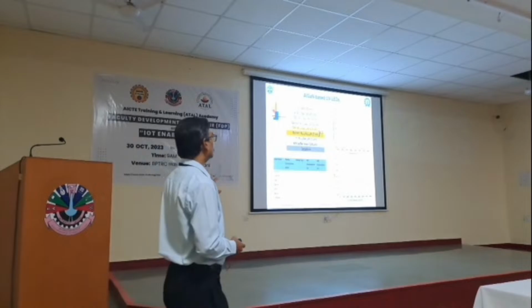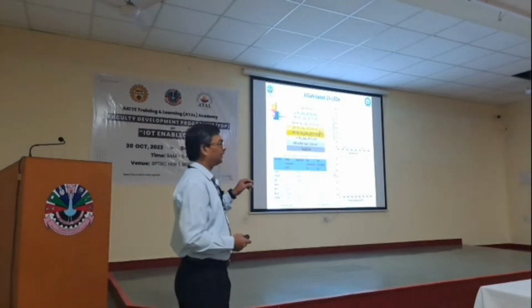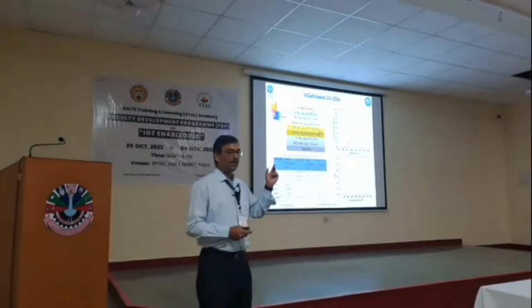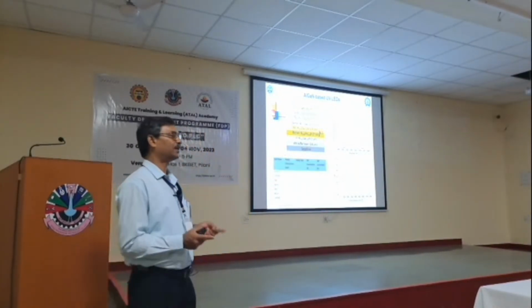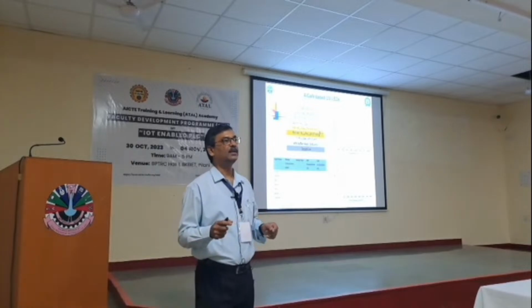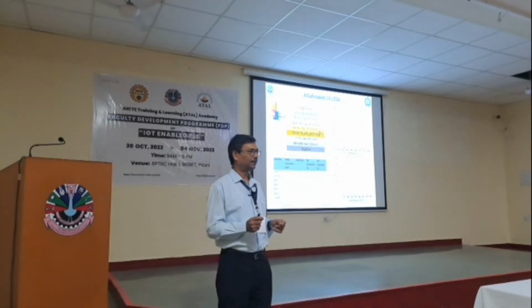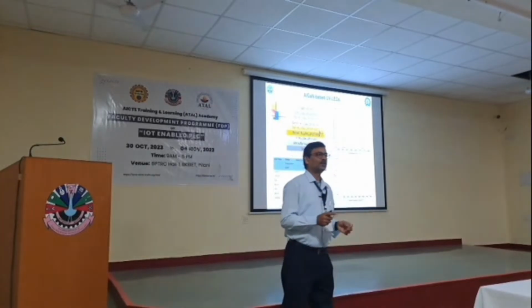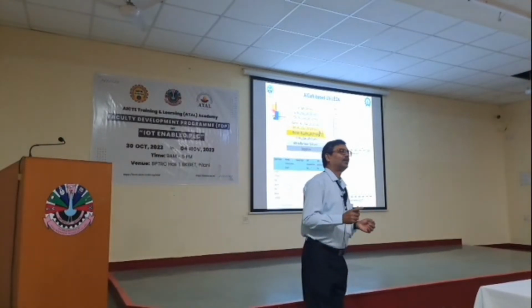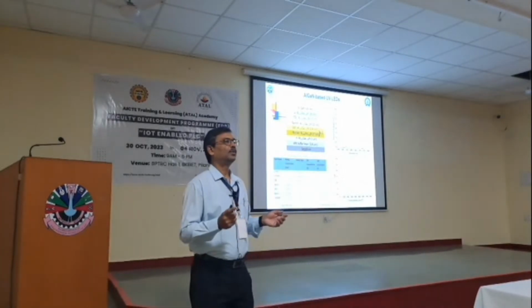Similarly, UV LEDs as well. For UV LED also, gallium nitride is the base material, and with aluminum composition we can go for emission towards UV light. So for blue and white, I just forgot to mention, whatever white LEDs we are seeing everywhere, indoor and outdoor application, blue is its basis. So for that we have to first fabricate the blue LED in the range of 450-460 nanometers emission wavelength, and after that we need to go for the yellow phosphor combination. So all of you know that blue and yellow light gives a combination of white.